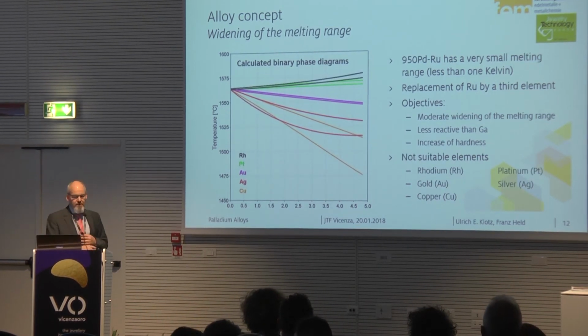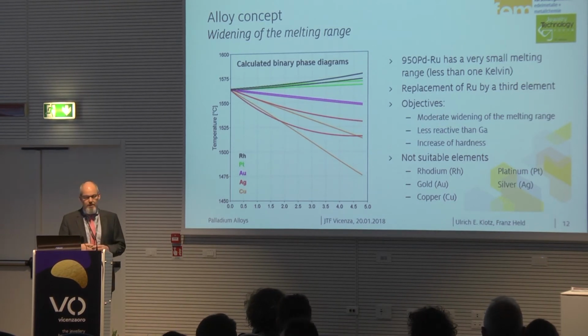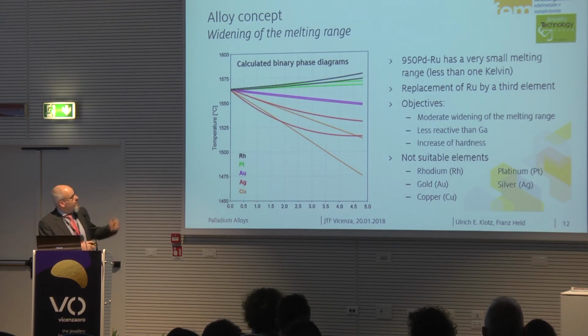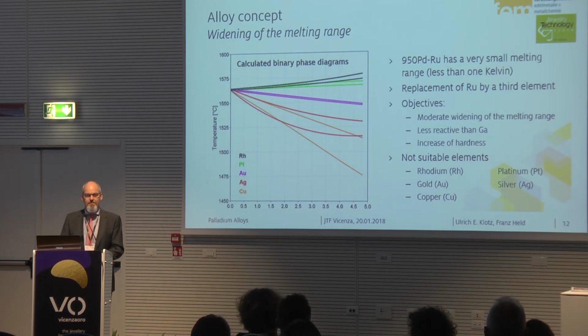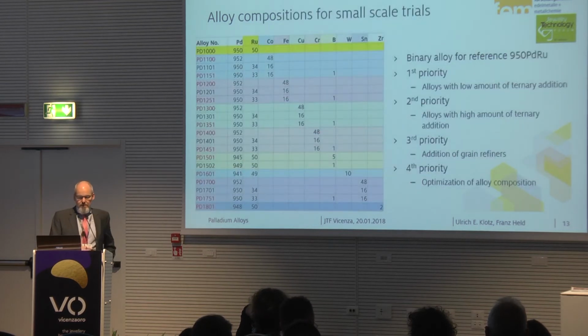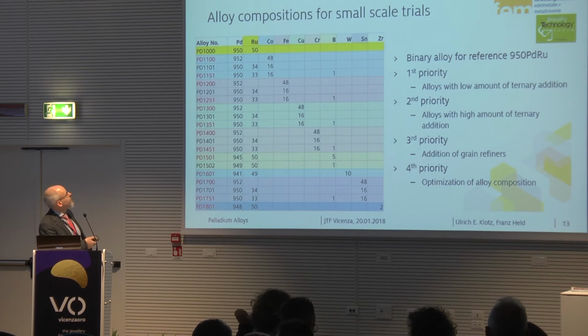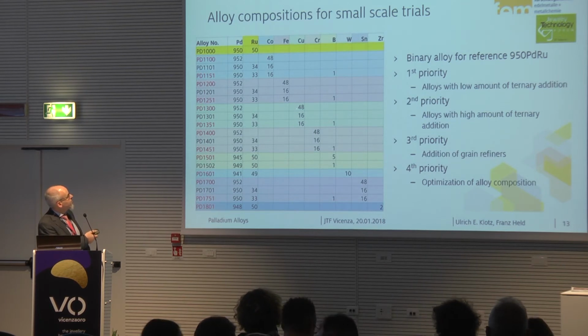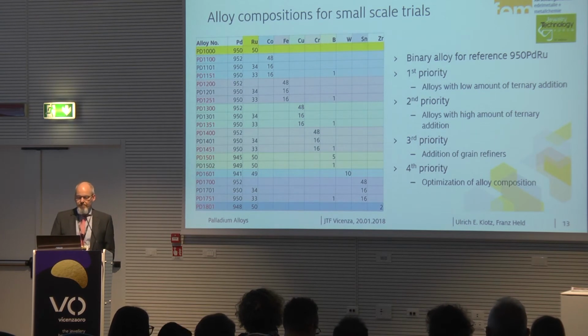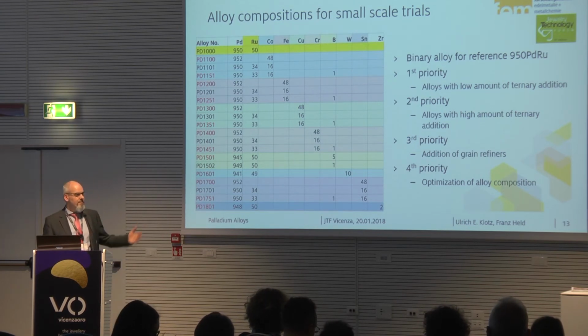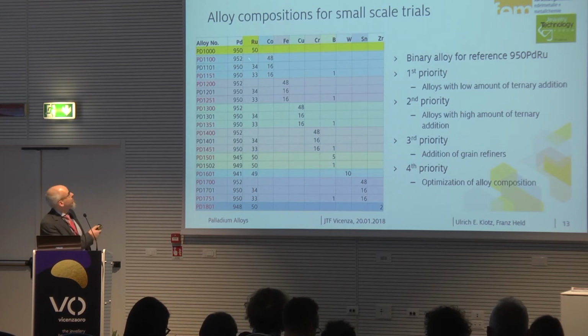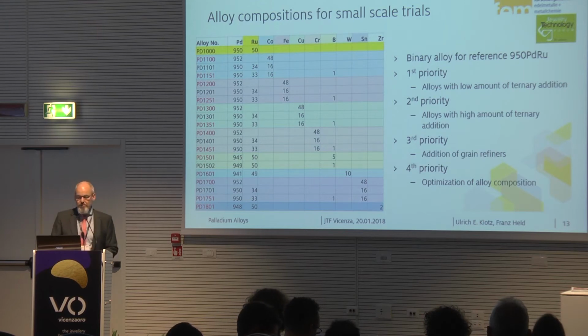There are more elements like rhodium, platinum, gold, silver, and copper. They also have effects on the melting range, but the effect on hardness of these elements is very low. Therefore, these elements were of less interest. Then here comes the first list. This is a selection of alloying elements that we prepared. We have palladium and ruthenium as the basis. Then we added cobalt, iron, copper, chromium, and so on. And with these basic binary alloys, we could make mixtures of many alloys that contain, for instance, palladium, ruthenium, and cobalt. And so we could vary the composition quite easily in a very effective way.